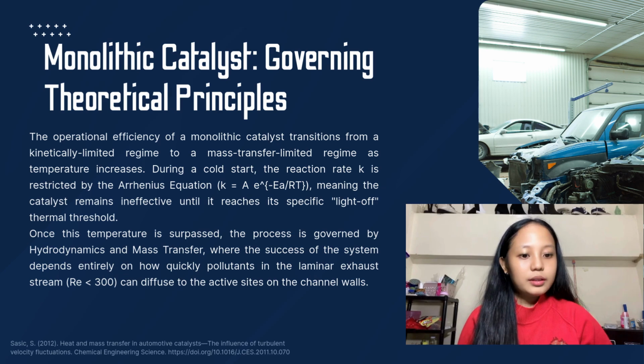Here's the clever part. Size matters. Because these channels have such a tiny hydraulic diameter, the exhaust gas doesn't swirl around in a chaotic mess. Instead, we keep the Reynolds number low, forcing the flow to become laminar. This isn't just for show, it's functional. In a stable laminar flow, the gas moves in predictable layers. This allows pollutant molecules like CO, HC, and NOx to migrate efficiently from the center of the gas streams to the walls, where the catalyst is waiting for them.